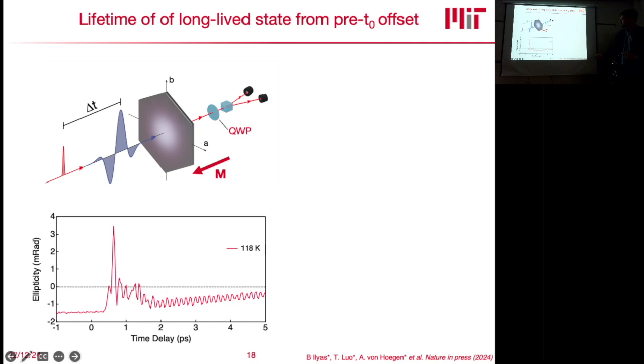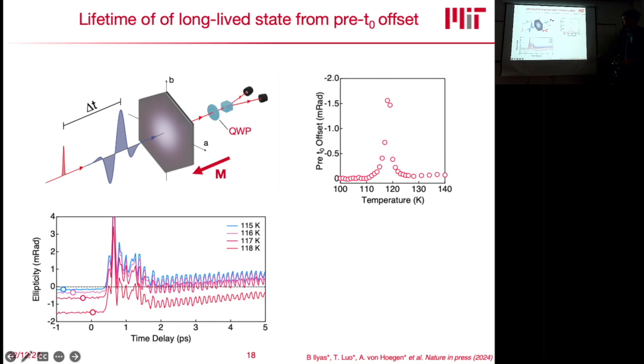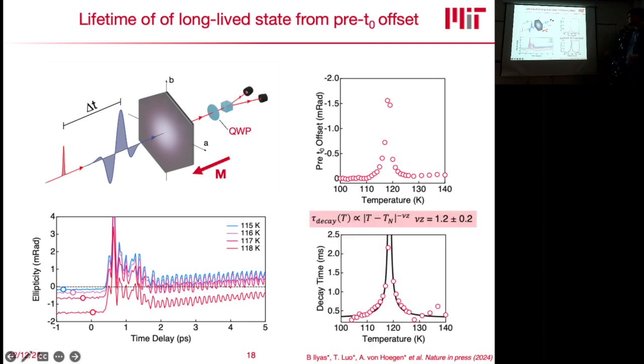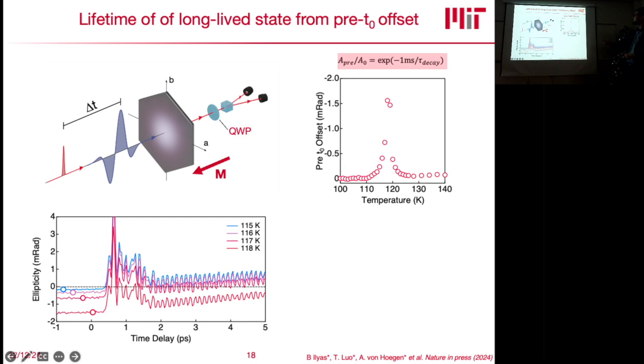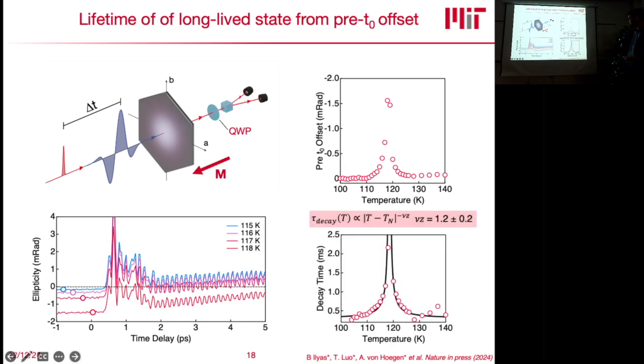That means that the state we're generating here, after 1 millisecond, has not yet relaxed back to its original ground state. This usually hints to heating, but we already know this is not heating in this case. So we can now take this pre-time zero signal and look at its temperature dependence to characterize the decay time of this photoinduced state. And again, we find that this pre-time zero signal, which we trace here with these dots, also diverges close to the critical temperature. So this also means that the relaxation time of this new magnetic state diverges. Because we have this formula, and we know the interpulse separation, which is 1 millisecond, we can work it out on this pre-time zero offset and reconstruct the decay time, which we find here at 118 Kelvin to be 2.5 milliseconds.